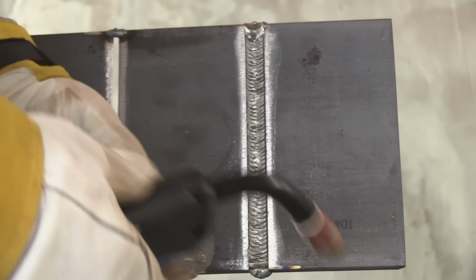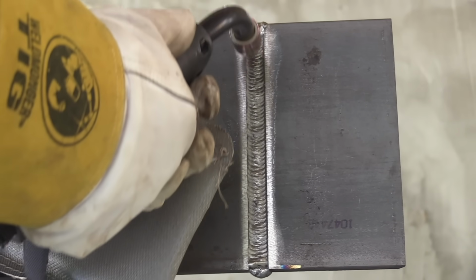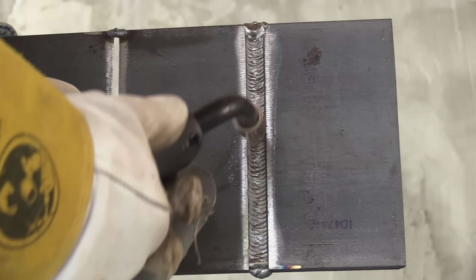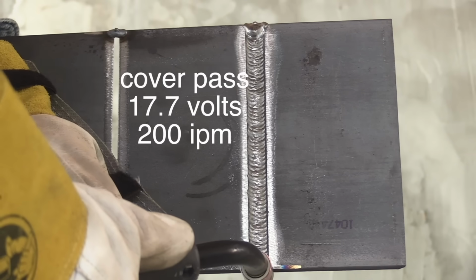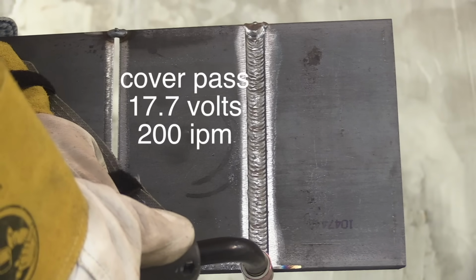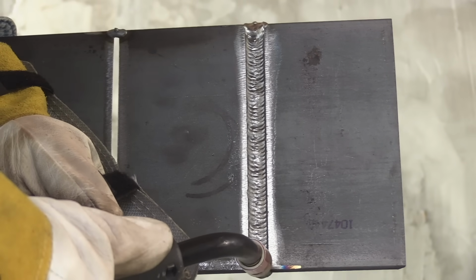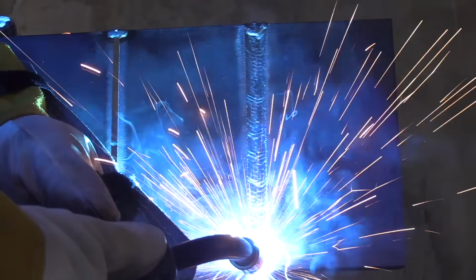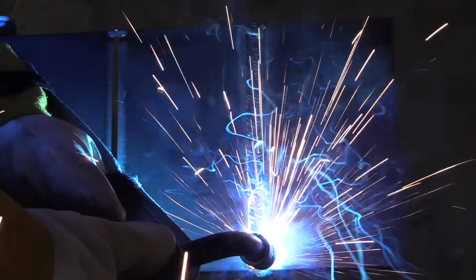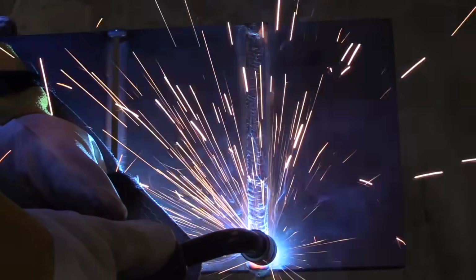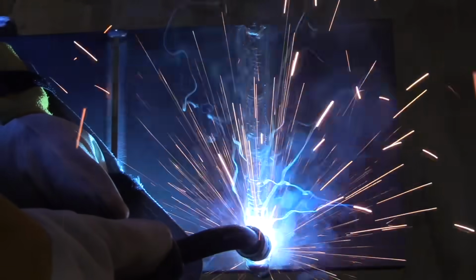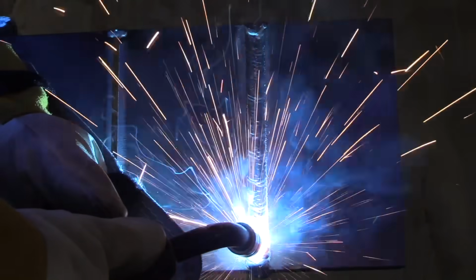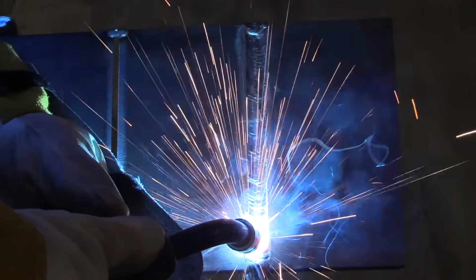Once again, your settings are going to be a good bit lower than the recommended settings on the inside of the MIG welder here. In this case, for this cover pass, I'm only using 17.7 volts, 200 inches a minute with .035 ER70S-6 wire. These same settings for this plate will work just fine on the same thickness pipe, as long as the bevel is the same and the gap is the same and the land is the same.